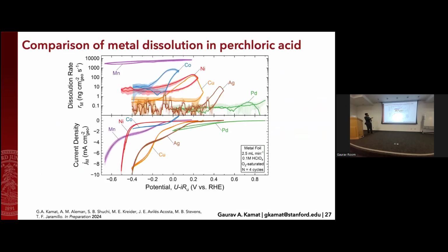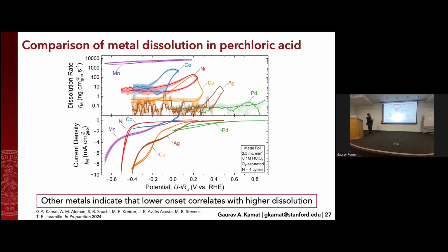Another thing we can do with this setup is compare the different metals in terms of their dissolution in a single acid. So these are all taken in perchloric acid, and we can see that they have vastly different onsets based on where this cyclic voltammogram is taking place. And you can also see that as this onset tends to get worse, you also tend to have a little bit higher rate of dissolution of your catalyst, which is a little counterintuitive based on what a lot of catalyst activity and stability trends tend to look like.